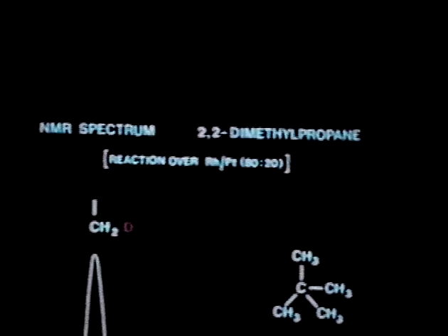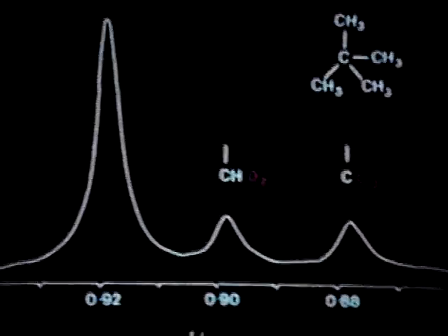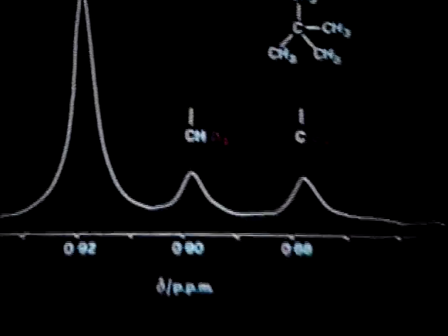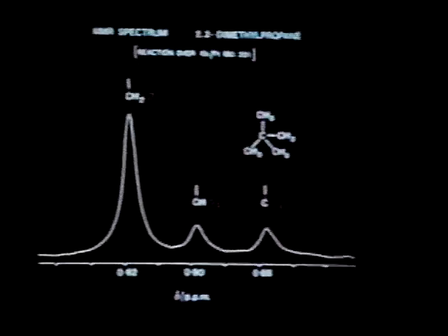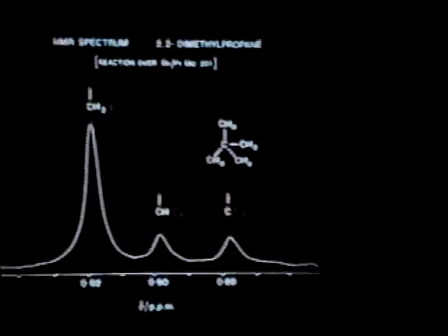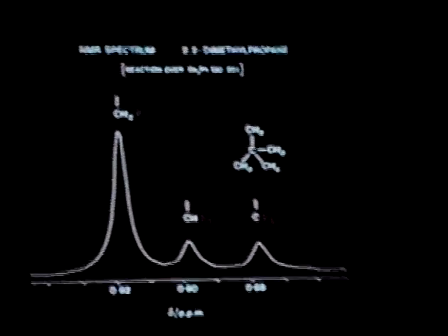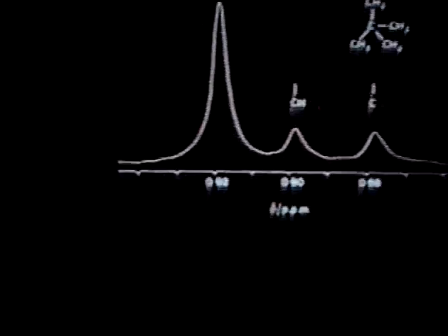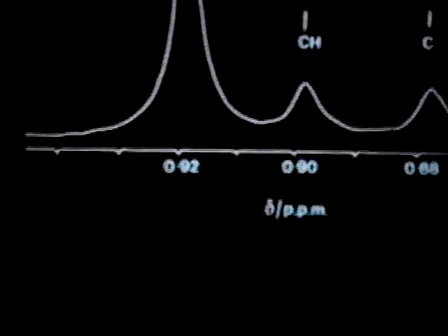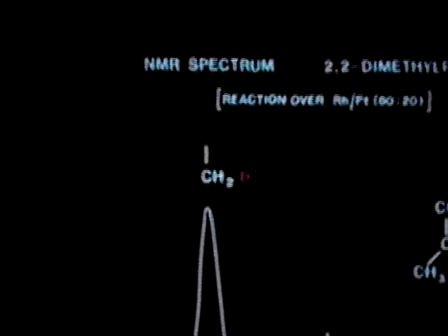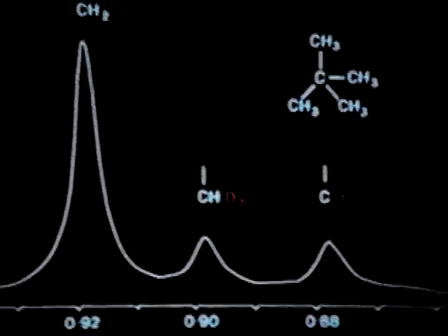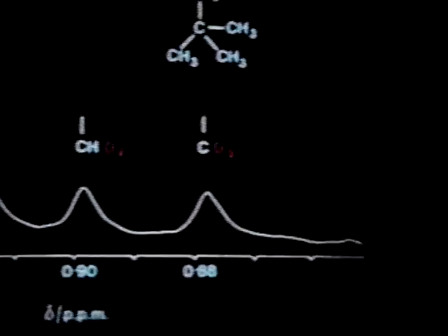This slide shows results with 2,2-dimethylpropane, in which one can detect very easily whether the methyl groups contain one deuterium, two deuteriums, or three deuteriums. The point being that if there is a second deuterium in the methyl group, it causes what is known as an alpha isotopic shift, in this case of 20 parts per billion, and if there are two extra deuteriums, in other words, the CD3 group, you get a double shift. Next slide.